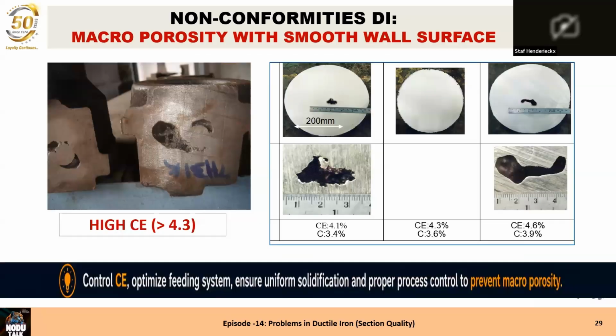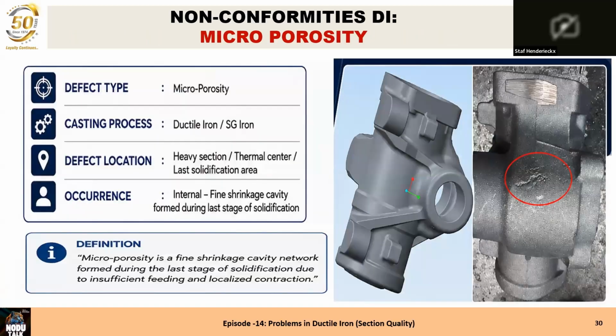Here you see typically how the smooth wall surface of a microporosity looks on the left side, and on the right side I have put some pictures. You see with 4.1 it's more a rough one, 4.3 theoretically it's no porosity, 4.6, you see it's a very smooth wall surface. And if you see microporosity with smooth wall, always first look at your carbon equivalent. Something is wrong over there.